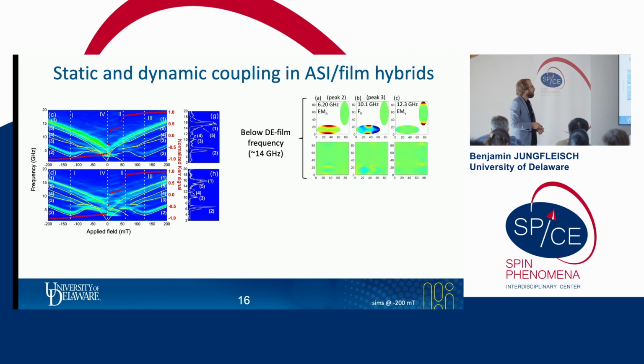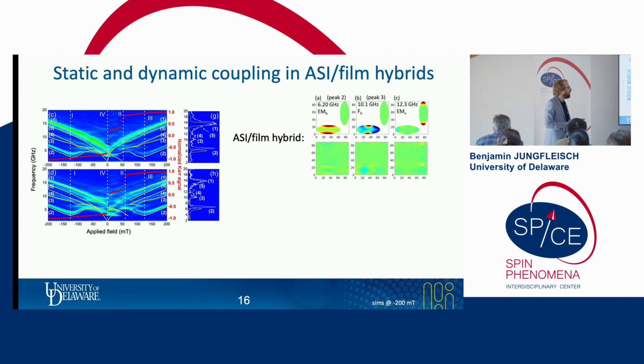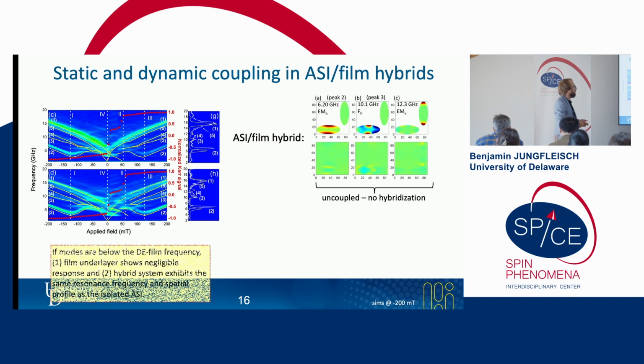So let's take a closer look and discuss the different modes. First, I'm going to focus on the modes below the Damon-Eshbach frequency, which is at 14 gigahertz for 200 millitesla field. So we have here peak 2 and peak 3, and another mode at 12.3 gigahertz. And we can immediately see that the modes are uncoupled. So the artificial spin-ice system and the thin film underlayer are not coupled. There is no hybridization. So if modes are below the Damon-Eshbach frequency, the film underlayer shows a negligible response.